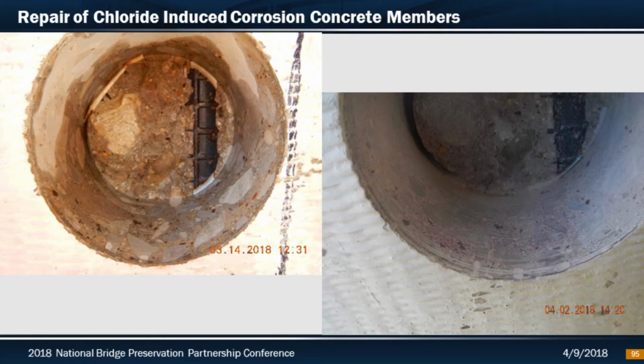It would be an amazing thing to assume that we've effectively stopped that ingress of chlorides and the continued problems that we were having out there. They did some cores, and their visual inspection actually kind of validated those conclusions. You can see there on the left, that's an exposed bar, and if we remember what it looked like prior to the original construction, that steel was in pretty bad way. So after the blast cleaning, we got a nice, decent looking rebar with very limited, or effectively no corrosion damage at this point.